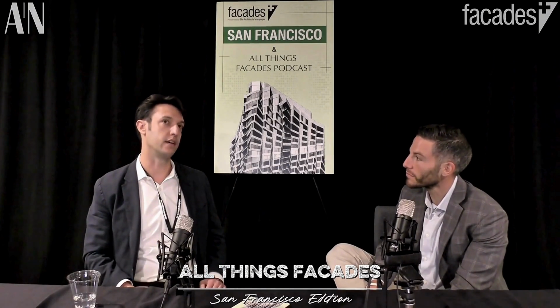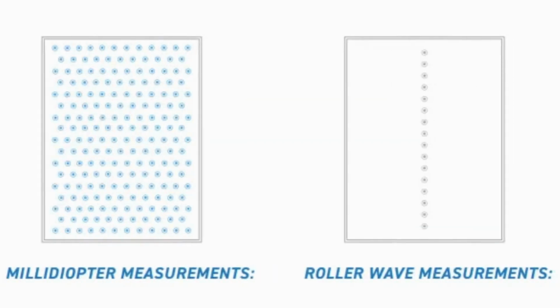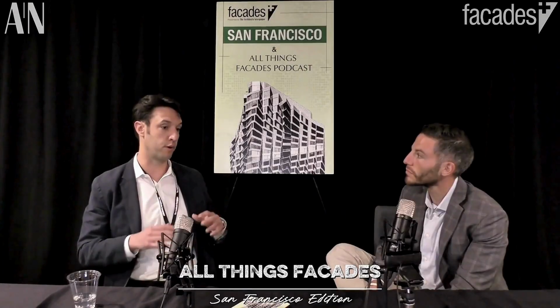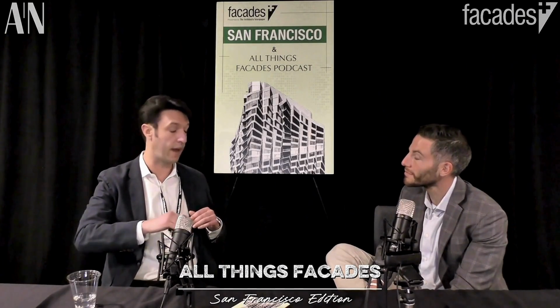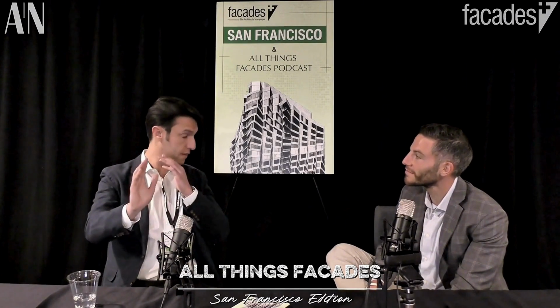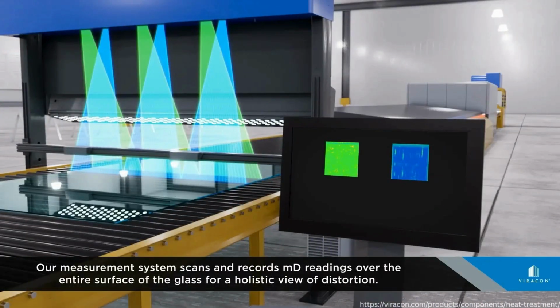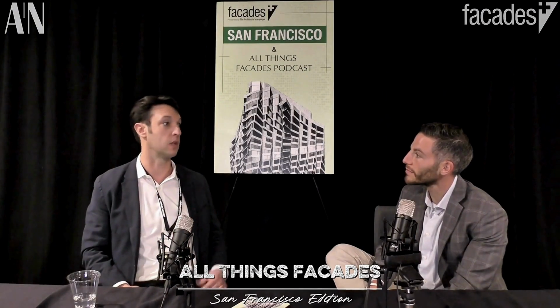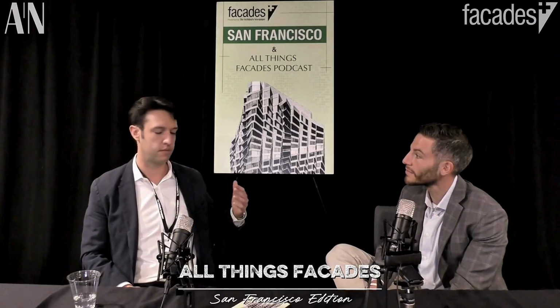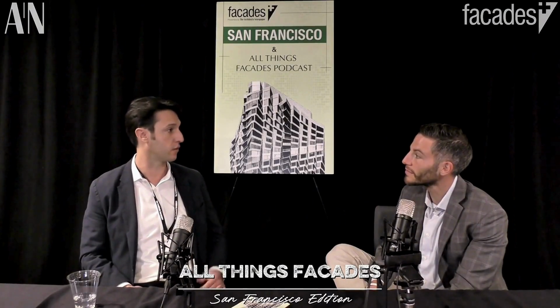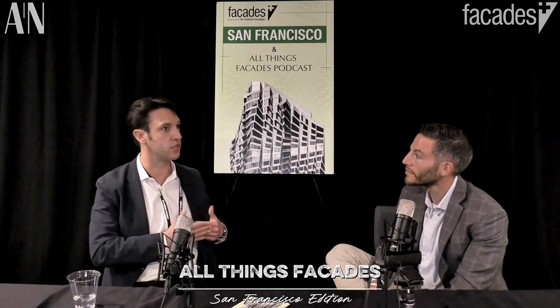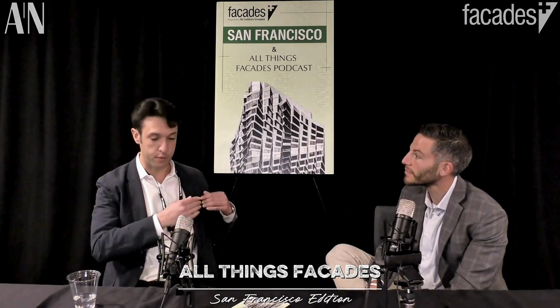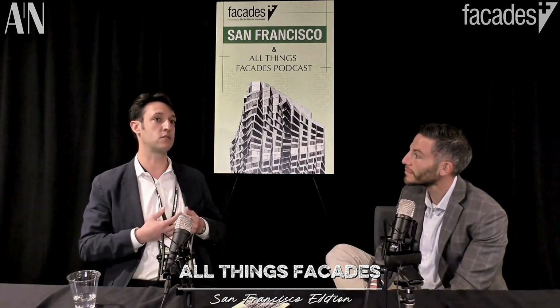And so we have developed a new specification tolerance using millidiopter, which is a much more holistic approach to measuring glass flatness. Rather than just that lineal peak to valley measurement, we're projecting thousands of data points onto the glass surface, measuring it. It's almost like a topographic glass map, if you will. Stuff like that is what makes Viracon great and cutting edge. We're always trying to push the industry to be better. Right now, our main push is flatter glass, and that's not just for us. We want the industry to go that way. It makes better buildings, right?